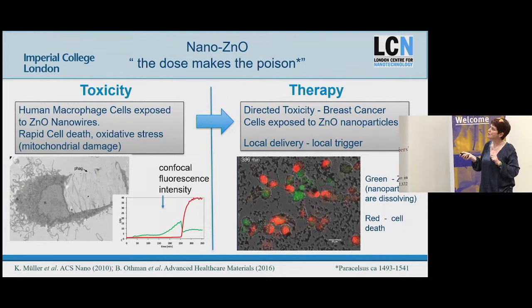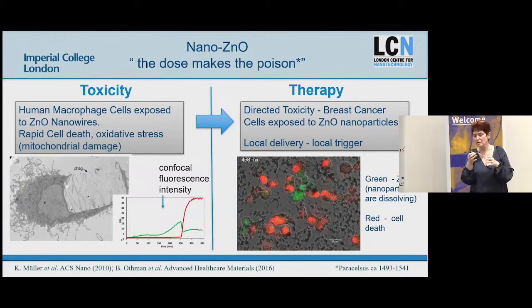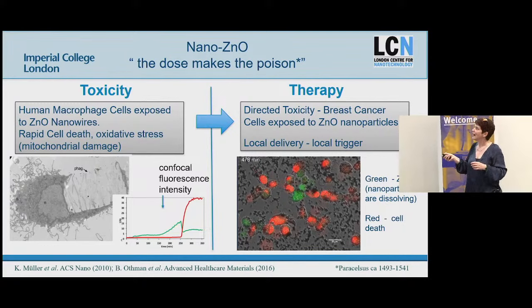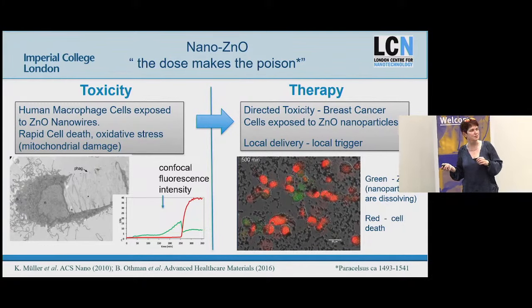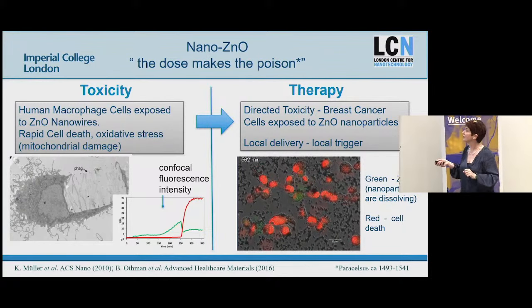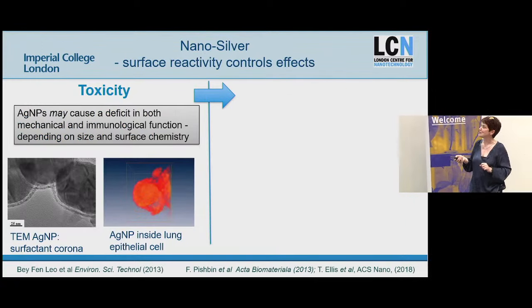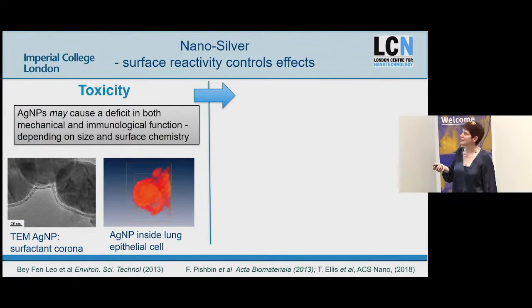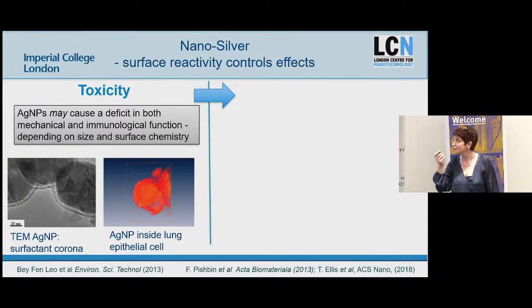What you find is it only goes green where the cell is, so it's not dissolving extracellularly. It's only when it gets inside the cell, in that intracellular lysosomal environment, that it dissolves. And they all dissolve at slightly different times. This heterogeneity of survival is actually a really important characteristic of breast cancer, which we don't have time to talk about. We see a similar thing with silver nanoparticles.